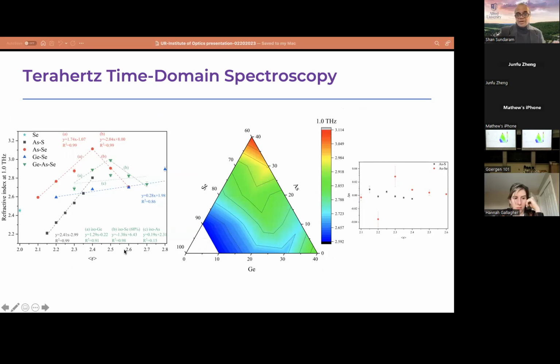And the one on your left, we are showing the 1 terahertz data set for all these glasses as a function of the average coordination number. And you can clearly see several sharply well-defined linear trends for arsenic sulfide, arsenic selenide. These are well-known chalcogenide glasses. But then there are glasses where the trends are not that obvious. We just wanted to plot everything to show you how some of the binary simple glasses fit this trend very well, and some of the glasses not so well. But you can see there are still several linear fits with decent R-square values here.